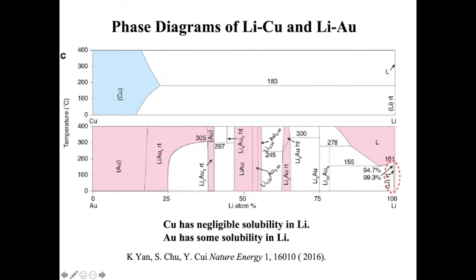What does this mean? It means when lithium is coming in during deposition, before lithium metal deposition happens, lithium alloys with gold, and it has the ability to dissolve gold away because gold has solubility in lithium. So lithium has this ability to make gold more and more look like lithium. After that, lithium deposition happens, and this gradual change really removes the nucleation barrier. But lithium on copper is a different story. They are very different in lattice constant and crystal structure. So lithium deposition has nucleation barriers.